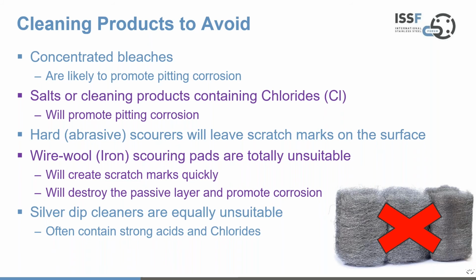Then a couple of things that you must avoid at all costs. Wire wool iron scouring pads are really unsuitable. Not only will they scratch the surface, they'll destroy the passive layer and promote corrosion because the passive layer will be contaminated by the iron and cannot reform. And silver dip cleaners are equally unsuitable because they usually contain strong acids and chlorides. So again, they start to damage the passive layer. So these are the things to walk away from. Don't use these, please.